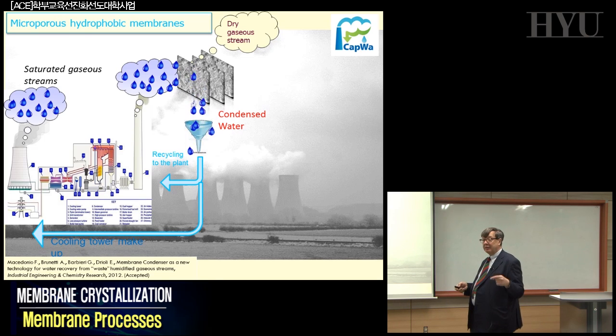This gas is normally arriving at a temperature of 90-95 degrees centigrade, high temperature, the one coming out from the chimney here. If you put on the membrane surface not 95 but 80 degrees, you cool down 8, 10 degrees, what is happening here is you can condense at least 20%, that was the goal of our project. But more than this, depending on what you want to do, you can have 50%, 90%, depending on the delta T between the temperature of the flue gas coming out and the temperature on the membrane surface. So if you realize a system where you don't warm up but you cool down, membrane distillation, the same module in principle, becomes a membrane condenser.